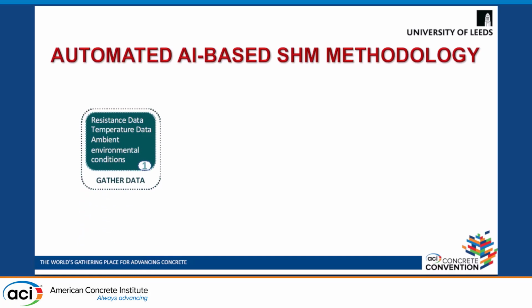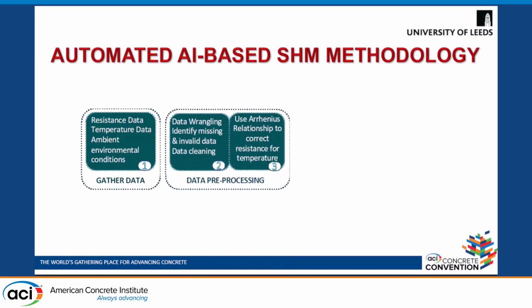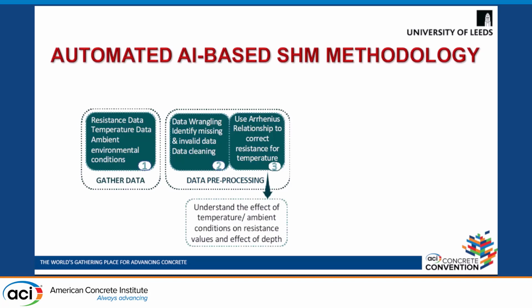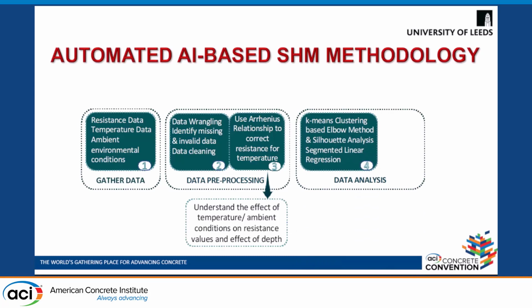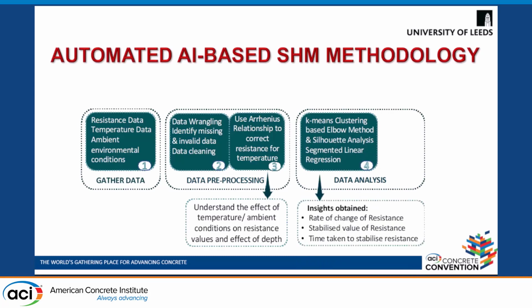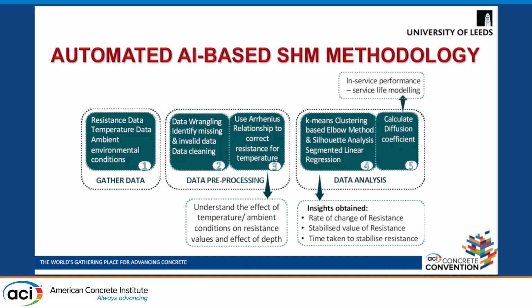This methodology is a 5-step process where in the first step you gather the data from resistance data, temperature data, and all the ambient environmental conditions data. It is then pre-processed where you identify the missing information and the invalid data and clean it, and use an Arrhenius relationship to correct the resistance for temperature to understand the effect of temperature and ambient conditions on the resistance measurements. Once the data is pre-processed, then you use a k-means clustering-based segmented regression, which provides us the insights on rate of change of resistance, stabilized resistance value, and time taken to stabilize the resistance, which then can be used to calculate diffusion coefficient values, and therefore that can be used in service life modeling for in-service performance.